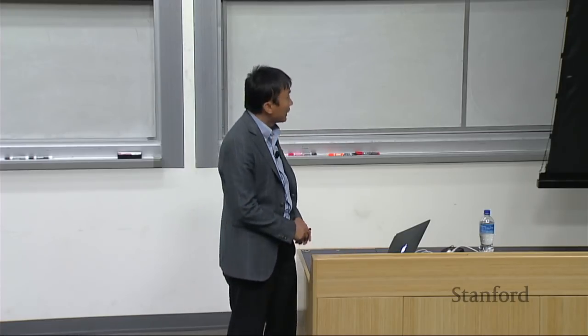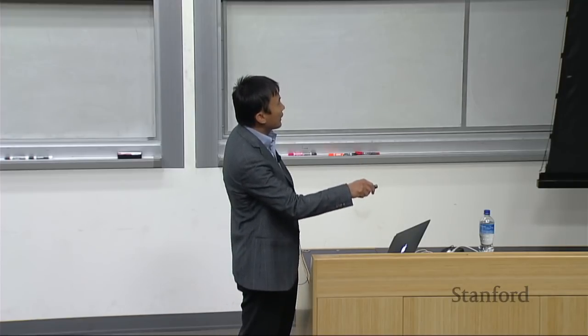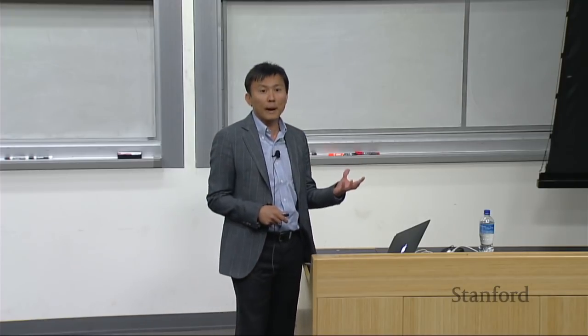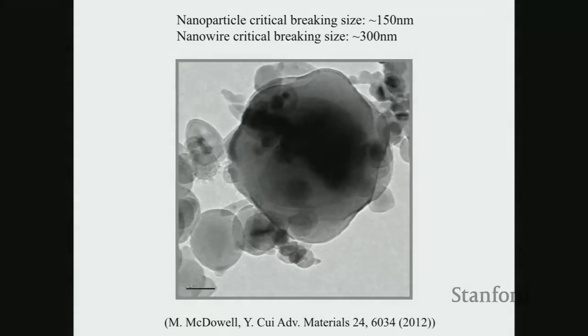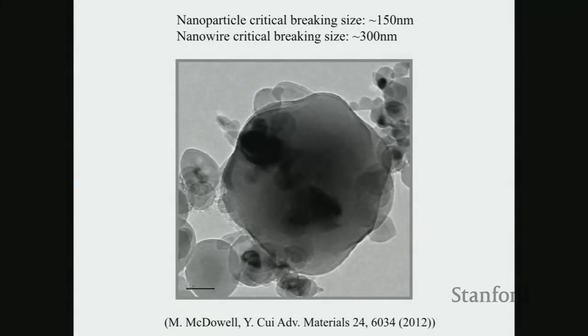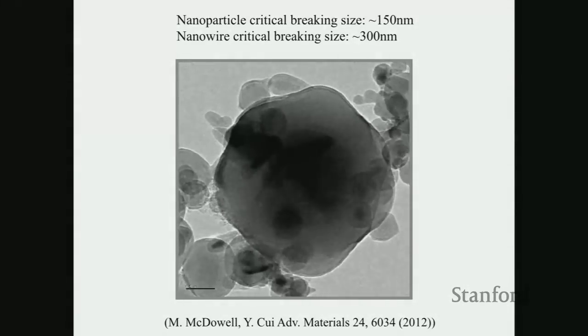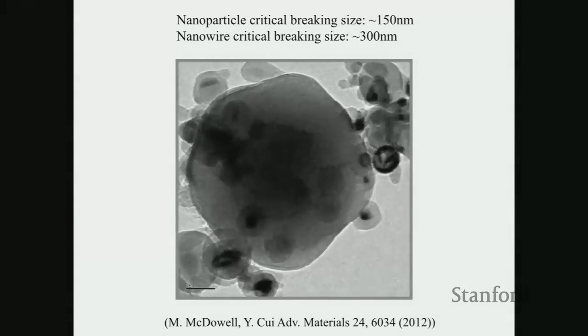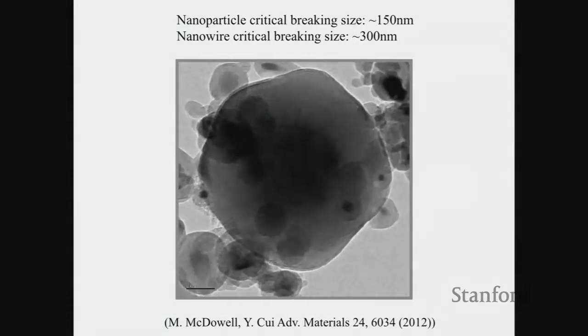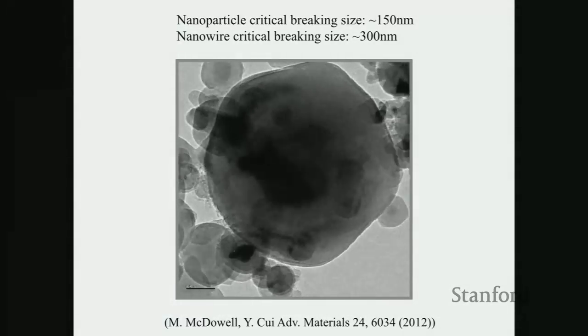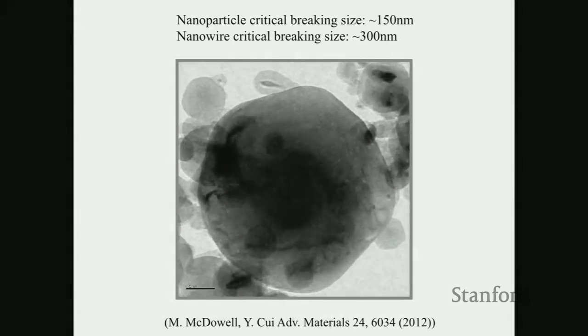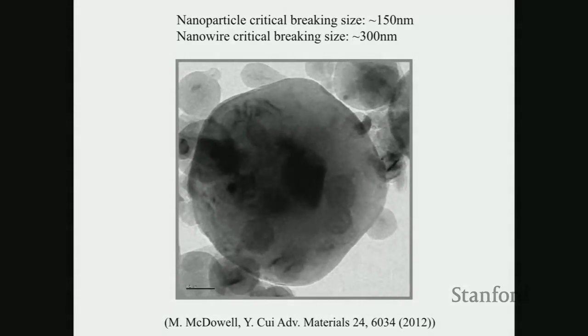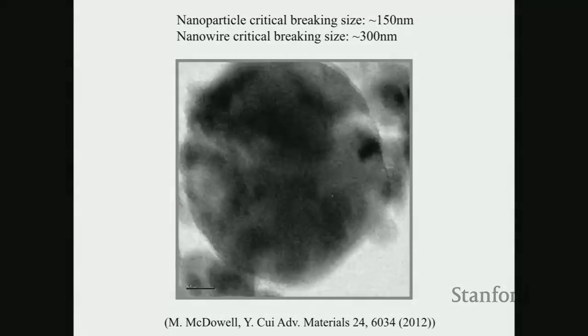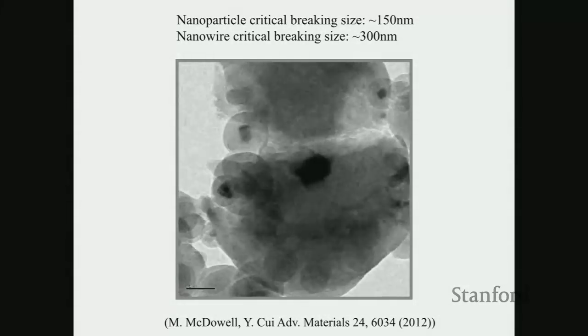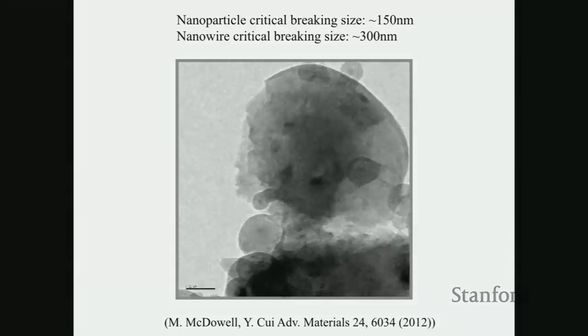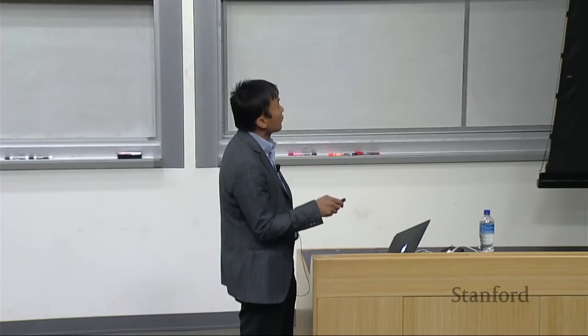It's quite dramatic. This is a silicon nanoparticle inside a TEM. We are doing in situ measurement, charging up this particle with lithium. It's 800 nanometers in diameter to start with. And you see significant volume expansion. After a while, this particle eats too much lithium and it's going to get broken. And this breaking causes the failure of the battery material. The first time you charge your battery, it's already dead. So that's the challenge we are facing.